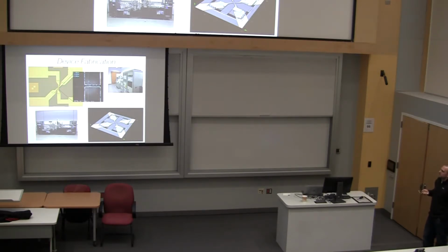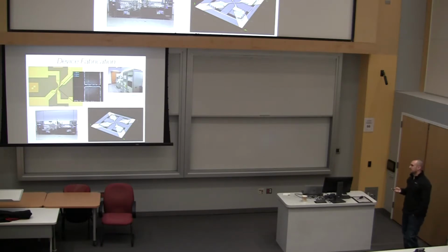You need a scanning electron microscope to actually see the junction. The junction is here. This is aluminum, and then you can't see it in black, but there's a small region of lead tin telluride in between those that facilitates the transfer of Cooper pairs from, say, the bottom to the top. Typically, the resolution we can get for this dimension, the spacing between two leads, is about 50 nanometers. We can push that down to about 30 nanometers now, doing some fancy lithographic tricks that I can tell you about if you're interested.